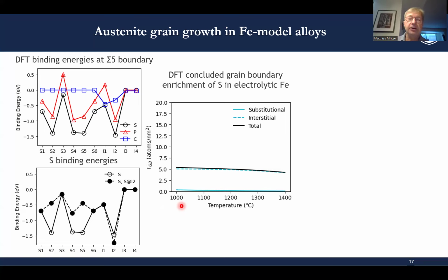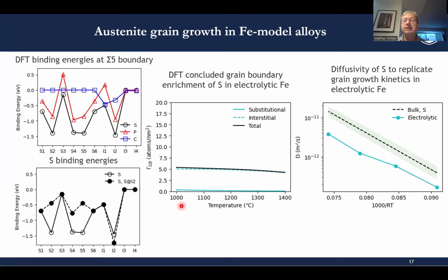We know the enrichment, or the effective binding energy of sulfur for this interface, for this grain boundary. We know the intrinsic mobility of moving the boundary without the sulfur interaction. And then the unknown to find, to replicate what we see in grain growth, is the diffusivity of sulfur across the grain boundary. And if we do this, we see that this diffusivity scales with the bulk diffusivity of sulfur. It's maybe a little bit smaller.